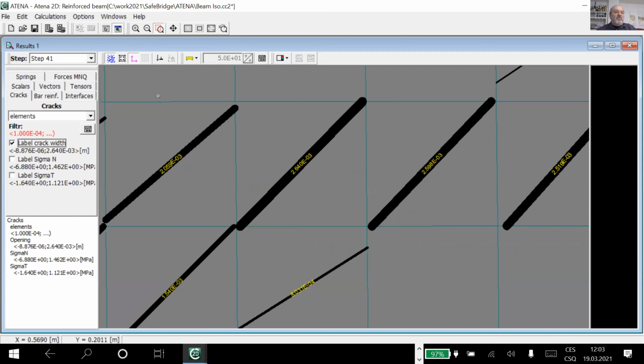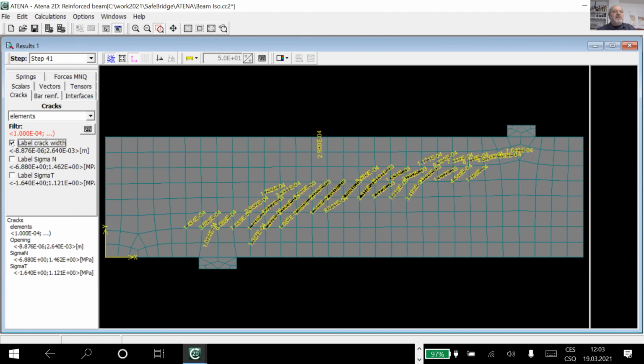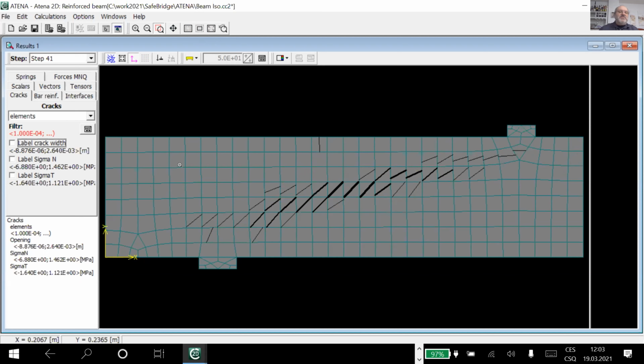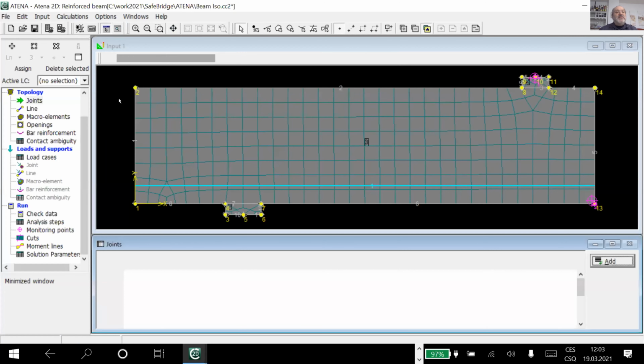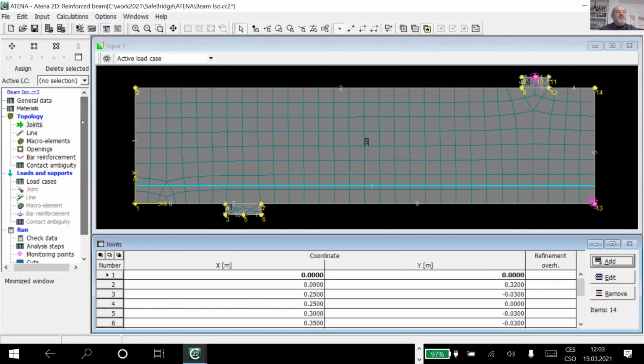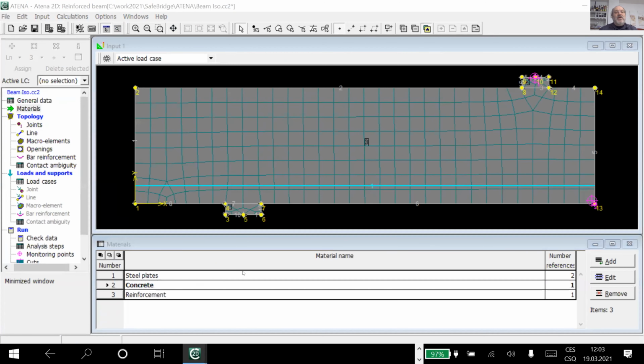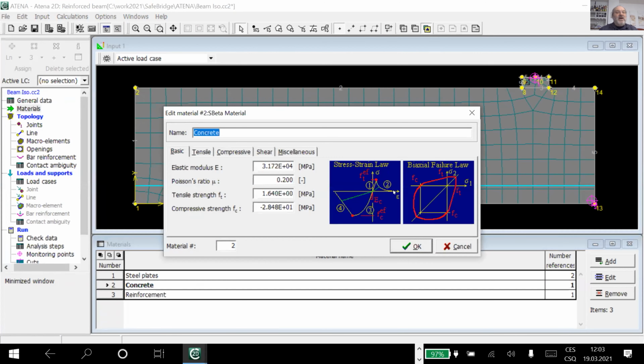Well, so for evaluation, the cracks are important, and also maybe some other values, but what is especially less interesting are stresses, because if you remember our stresses, if we check the definition of material in concrete, they go up and again down. So if you follow the stresses on the descending branch, they will actually diminish in the damaged region. So they don't say anything, and you don't know if you are on the ascending or descending branch.